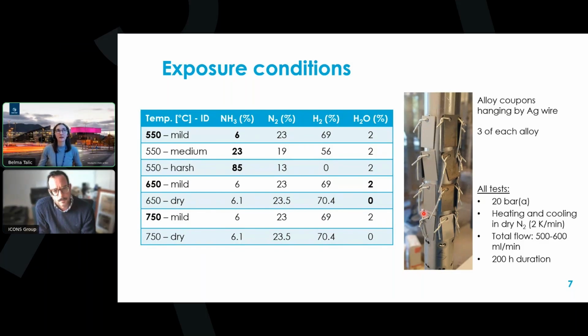Generally, under most of the conditions, we haven't really seen any systematic variation in the mass gain that corresponds to the direction of ammonia flow. The only exception was at 750 degrees and dry conditions. But in that case, we had quite a lot of cracking in the reactor. If I remember correctly, we went from 6% at the inlet to slightly below 1% at the outlet. So in that case, we saw some variation, that the sample placed on the top was slightly more affected than the sample at the bottom.